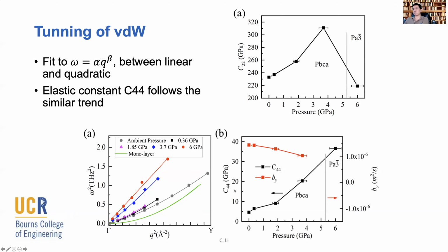And this is consistent if we fit this with a more elastic, continuum limit model, where we describe the elasticity of the system by a certain set of elastic constants. And you can see that with the increase of pressure, there's definitely an increase of certain elastic constants. And that tells you the system is going through an evolution, from a van der Waals type interaction suddenly into a quasi-covalent domain. But that happens well before the phase transition itself. Okay.